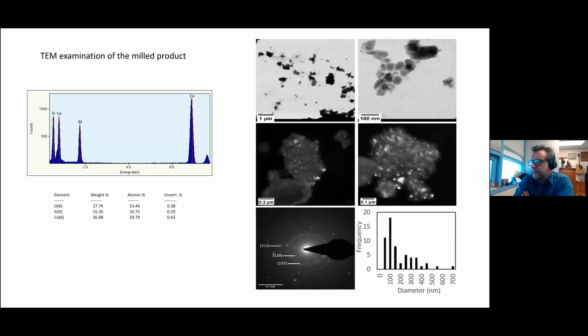We performed some TEM experiments to look at the product. So our cobalt olivine is really pure. It doesn't have any other elemental contributions. We have a grain size distribution that is not particularly sharp, but has a peak at about 100 nanometers, and some particles are as small as 20 nanometers.